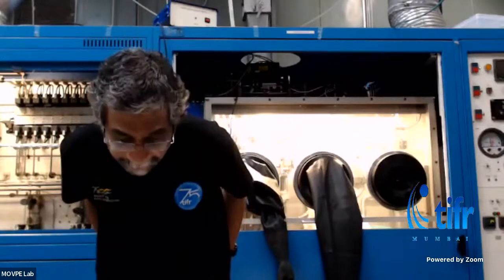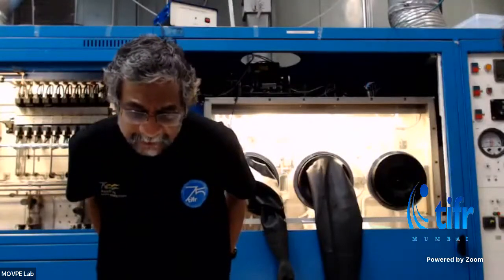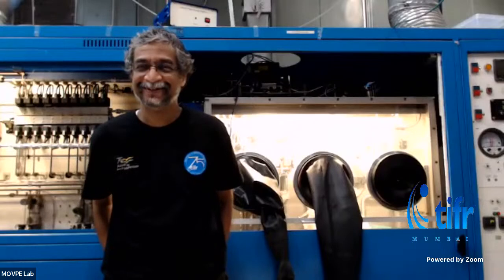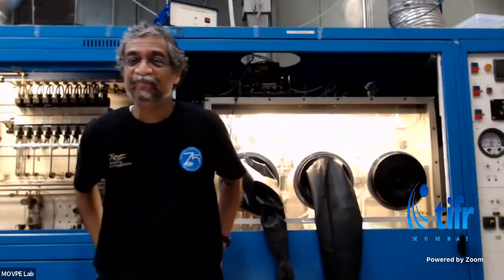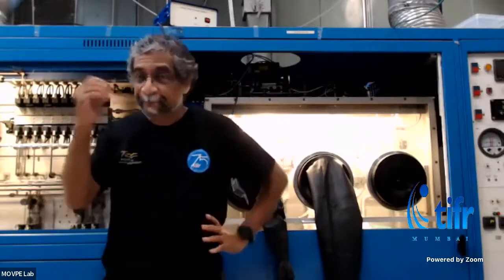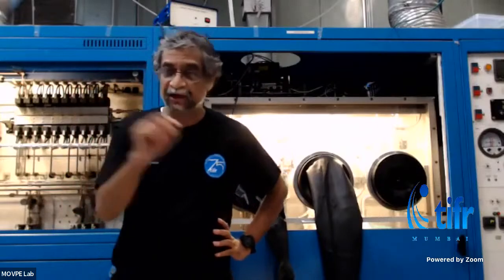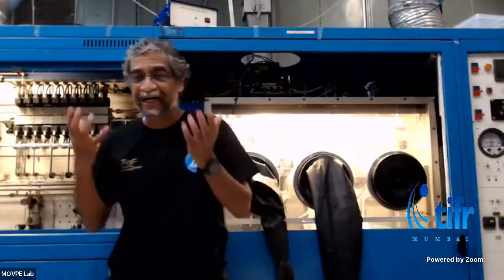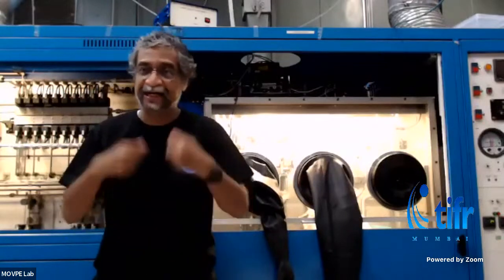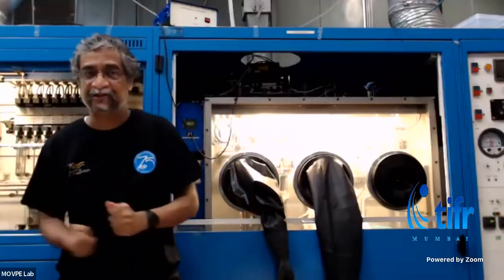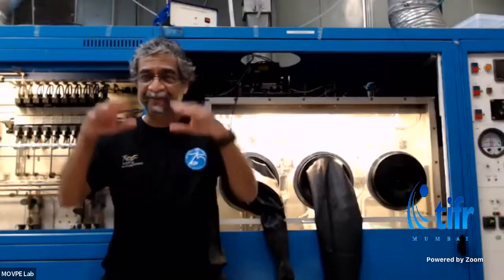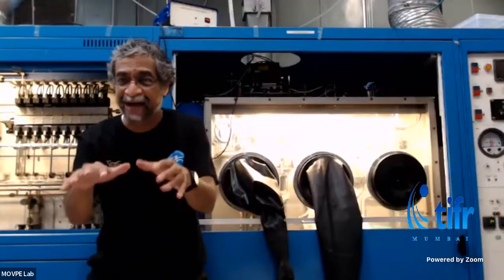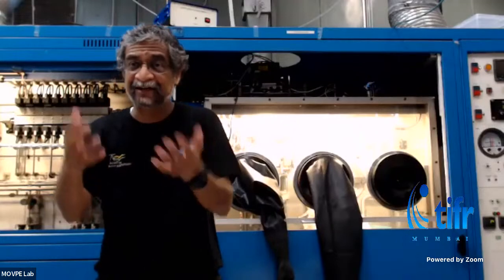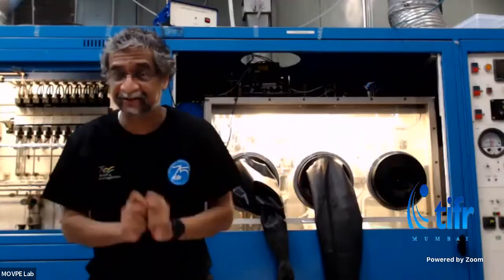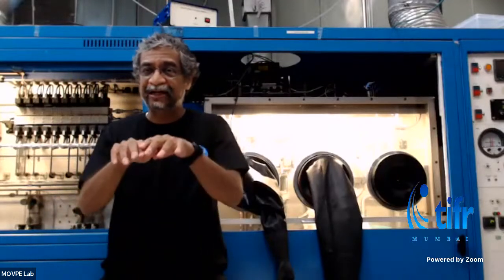Okay. Arnab asks, does cooking at high temperature probably result in a tasty semiconductor? No, sorry about that. This is just a joke. I mean, you showed some very high temperatures in your machine. Well, the temperature depends on the material you're growing. If you want to grow indium nitride, indium phosphide, indium gallium arsenide phosphide, you will grow them at perhaps 650 degrees, 700 degrees max. Sometimes indium nitride is 530 degrees.